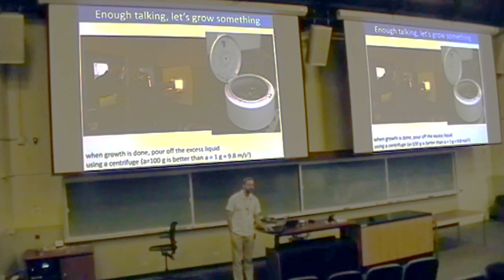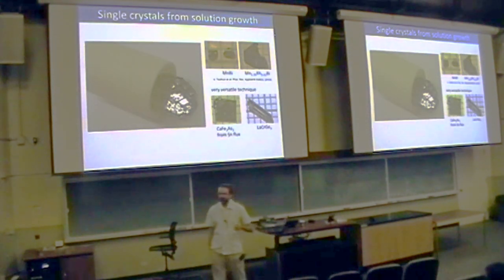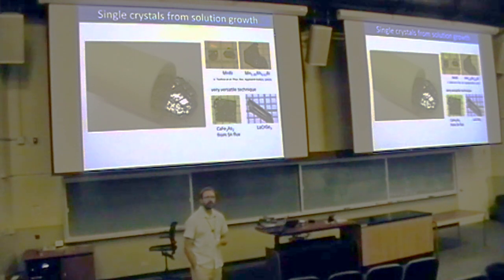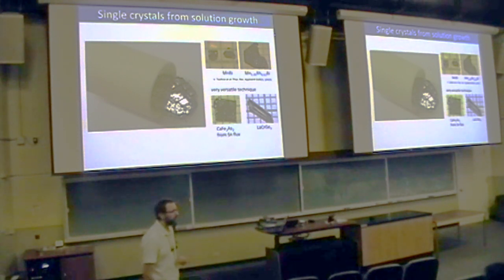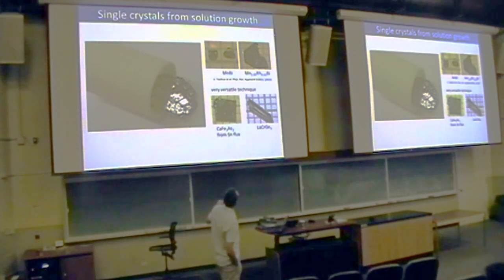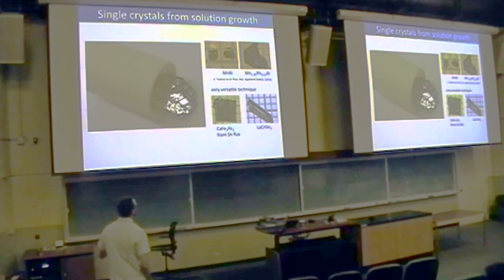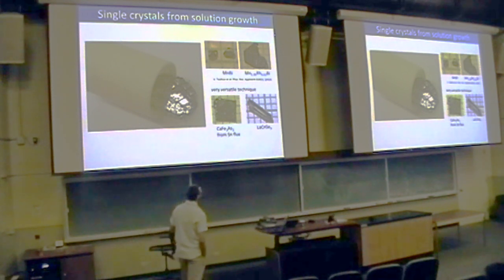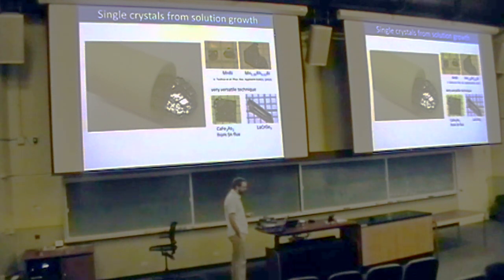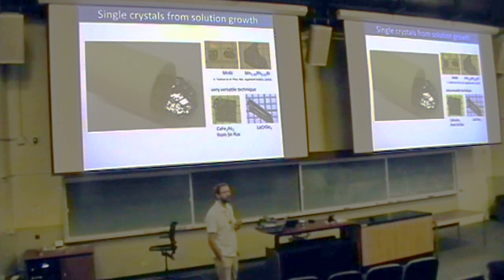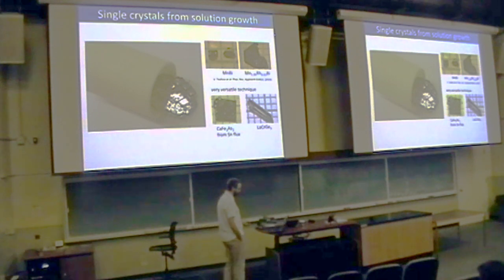And so you use this technique, which is solution growth, and you can grow many kinds of crystals. Manganese bismuth. You can even try to do substitutions by adding other elements and reproducing the exact same synthesis. Actually, when you do this, sometimes you get surprises. Here we actually found a new crystal with a completely new structure when we tried this. And you can go to other compounds too, iron-based superconductors, other kinds of 3D ferromagnets, but basically a very rich, very simple, rather cheap and very versatile technique for crystals.